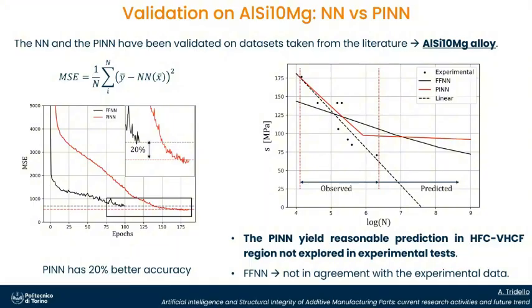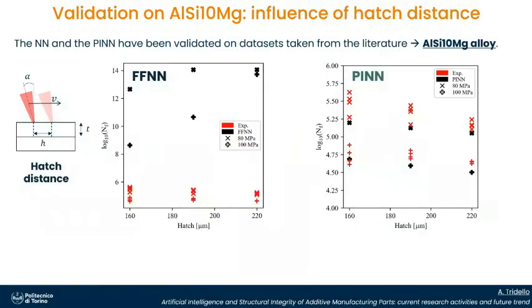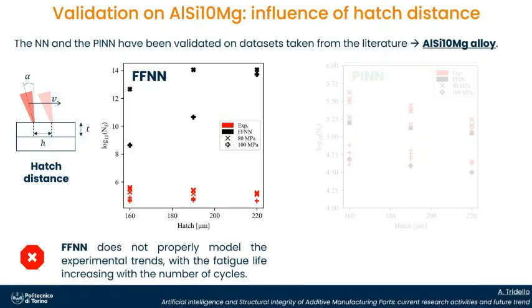Here you can see the physics-informed neural network. This red curve performs quite well also in the very high cycle fatigue life range, for which we have no data. In this case, on the other hand, we have not very good prediction without embedding physical knowledge. So this underscores this importance. And this is also visible here. Here we have two stress amplitudes, 80 megapascal and 100 megapascal, and we predict the influence of the hatch distance. It is a widely known parameter. If we increase the hatch distance, the fatigue response decreases. Okay. For the feed forward, the black box approach, we are far from the experimental data, and the trend is not respected.